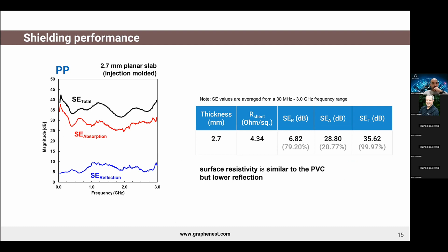Let's now look at G-Shield made of PP. Again, on the left, we can observe the shielding effectiveness as a function of the frequency, depicting again the reflection and absorption mechanisms as a function of the frequency. In this case, we are talking about a 2.7 millimeter planar slab, and instead of being extruded, it was injection molded. Our polypropylene G-Shield offers similar performance to PVC. However, as you can see, and if you can remember the last values, the reflection mechanism has a smaller role, so more absorption. Even so, this material promotes with this thickness 35.62 decibels of shielding, which is 99.97% of the power of the wave being attenuated.